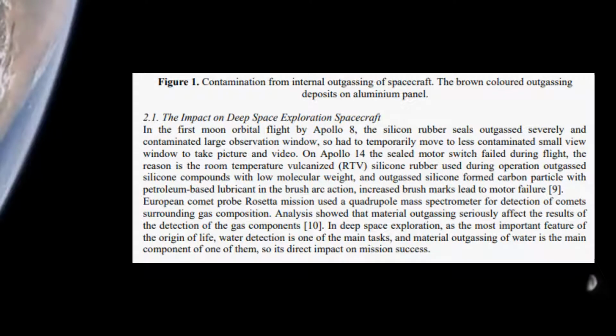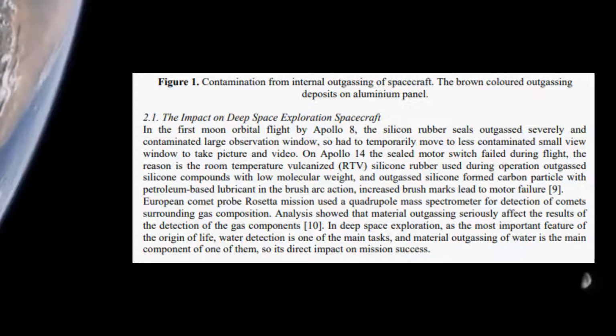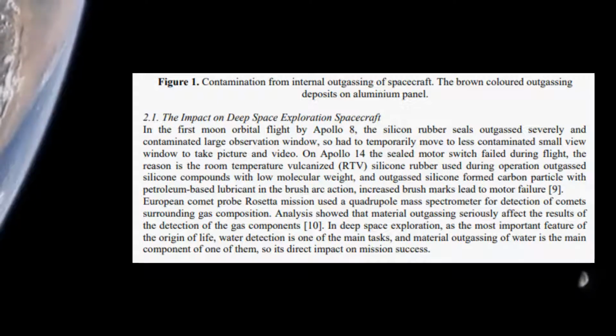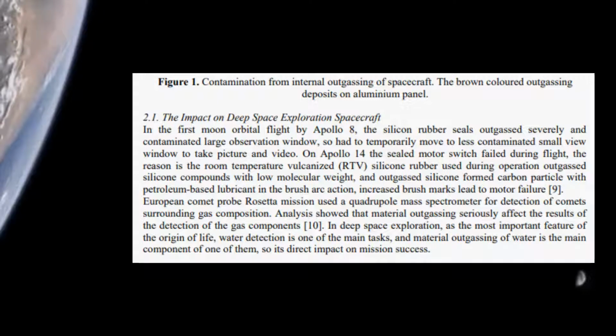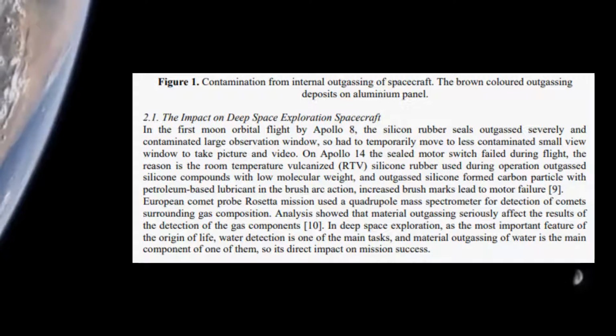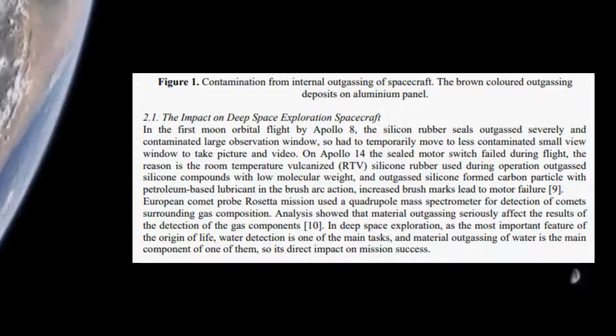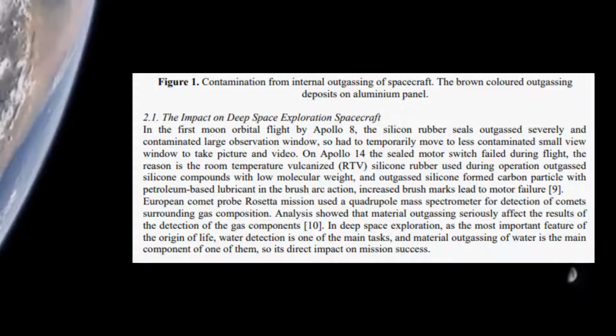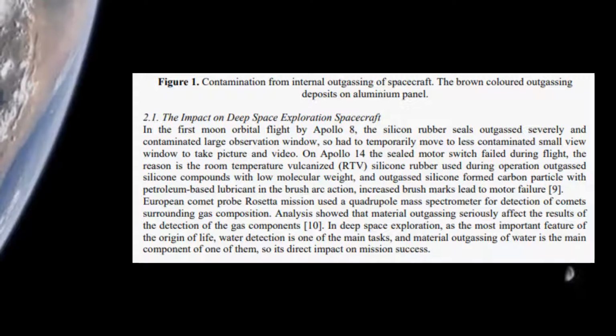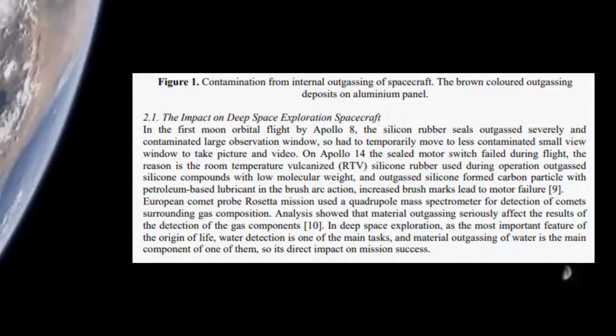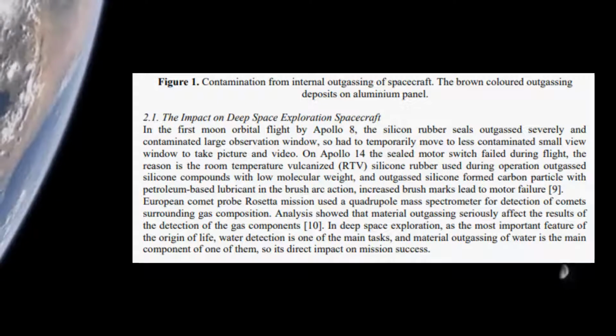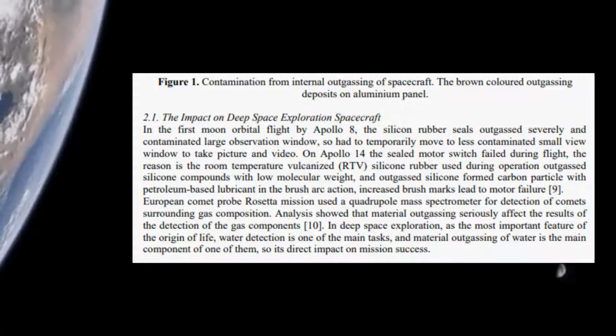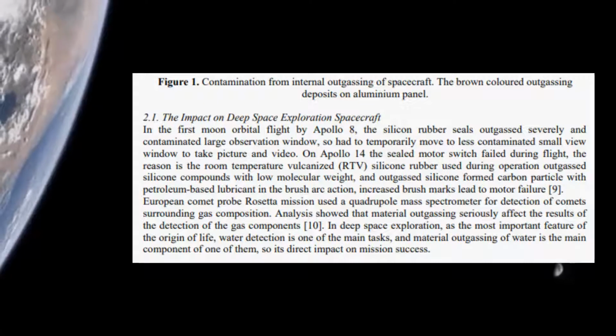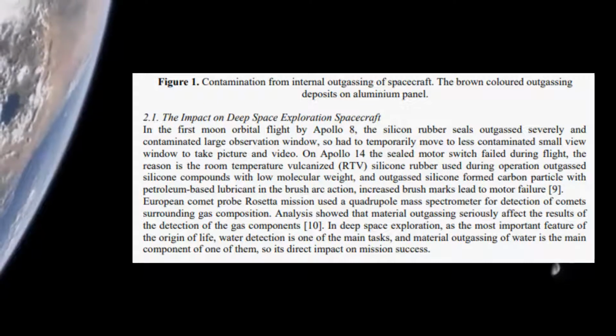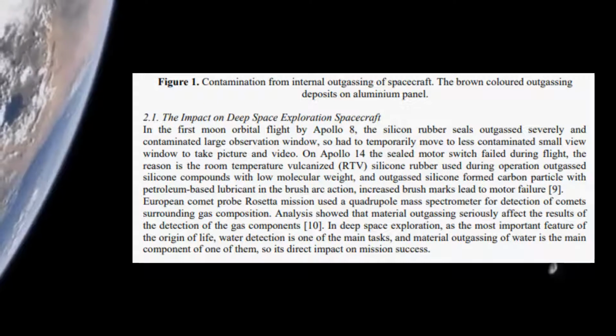2.1. The impact on deep space exploration spacecraft. In the first moon orbital flight, Apollo 8, the silicone rubber seals outgassed severely and contaminated the large observation window, so the crew had to temporarily move to a less contaminated small view window to take pictures and video. On Apollo 14, the sealed motor failed during flight. The reason is that the room temperature vulcanized RTV silicone rubber outgassed silicone compounds with low molecular weight, and the outgassed silicone formed carbon particles with petroleum-based lubricant in the brush action.